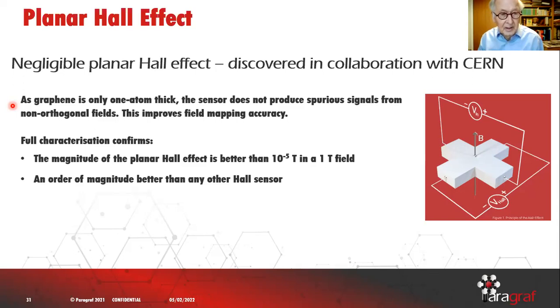In the tests at CERN, the planar Hall effect is better than 10 to the minus 5 Tesla in a 1 Tesla field. So it's actually negligible, an order of magnitude better than any other Hall sensor.